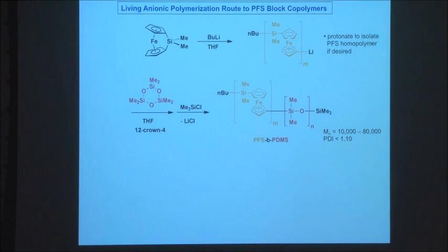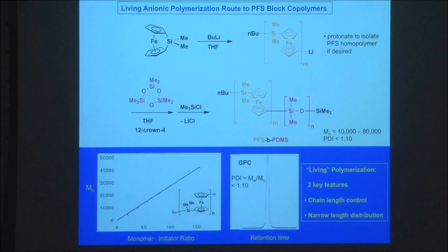Now, to illustrate the living polymerization, because we're going to come back to this concept later in the lecture, if we just consider this first step here, this illustrates the living nature of the polymerization. If you do this polymerization, you can take this living polymer you generate and deliberately terminate it by adding, for example, isopropanol, which will put a proton on the chain end. And if you do this, you can show a number of important features about this polymerization. The first is you can control the chain length, or the molecular weight of this polymer, simply by the ratio of the monomer to initiator.